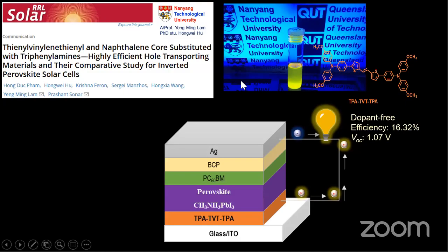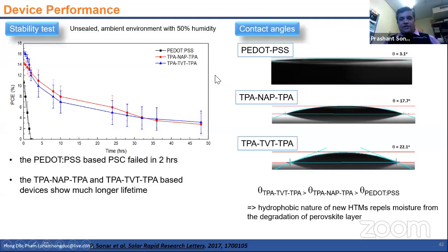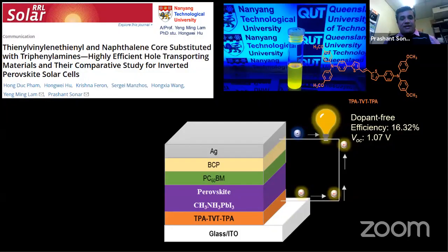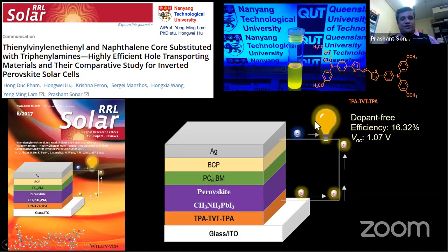Okay, so we got the contact angle measurement. PEDOT:PSS is a highly polar polymer, and you see the contact angle is very lousy, whereas for our material we get quite an okay contact angle. Don't compare this contact angle with our earlier molecule, which was too good. These were still with additives, that's why the contact angles are low. But again, we got a cover picture for this one.